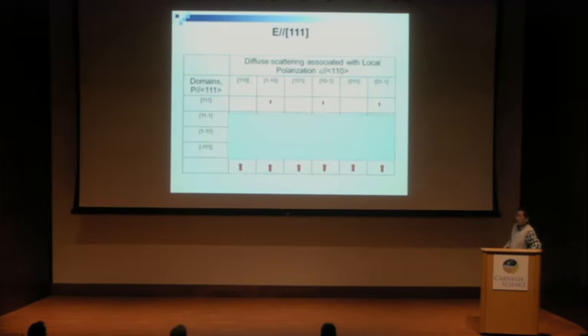But if we apply a field cool in a 111 field, it has a preferred 111 domain and suppresses the other 3 domains. It makes the 3 polarizations associated with the 111 domain enhanced, and the other 3 kinds of diffuse scattering, coming from local polarization not associated with the 111 domain, suppressed.